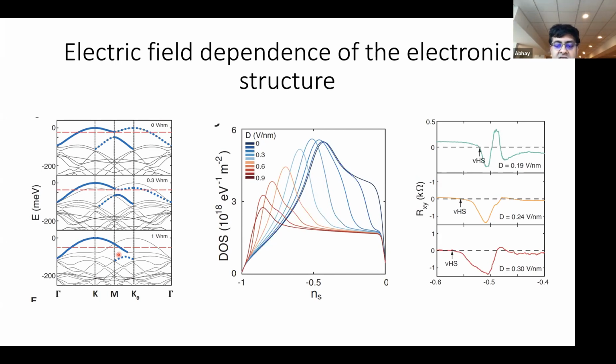Now, interestingly, if you look at all the STM experiments and put them together, you'll notice that some of them have very different values of electric field than others if you convert it. I think what happens is that with these tips, very often you'll have some insulating piece of junk that's very charged stuck to your tip, and this piece of junk is acting as a gate. So it's not a reproducible way of doing anything, but if you do this 5 different times, you'll find different electric fields. We're thinking about ways by which, if you have a gate which ends and you're close to the gate, the field will still leak over and you can measure it. We've done this for graphene, but the TMDs, not so far. Yes. Yeah.